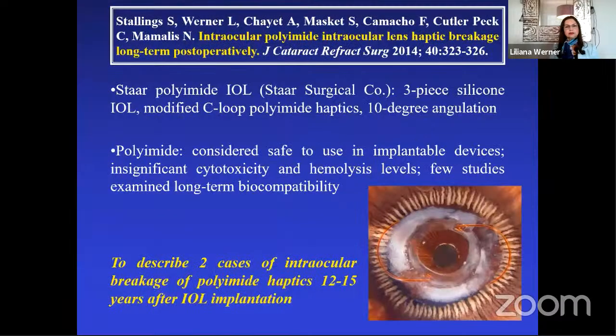I take this opportunity to comment about these very interesting cases related not to the optic material, but to the loop material of 3-piece silicone lenses. The loops can be made of different materials, including the one shown here, the polyimide. Few studies evaluated the long-term biocompatibility of this material. We described 2 cases where there was a spontaneous breakage of the haptics of 3-piece silicone polyimide lenses 12 to 15 years after IOL implantation.